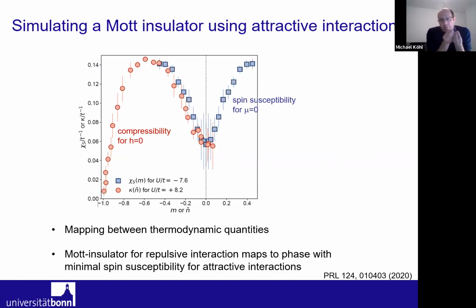Now, for the other case, for attractive interactions where we have these local pairs, we have to ask the question, what is the equivalent of the compressibility in the density sector, but now in the spin sector? And that is, of course, the spin susceptibility. So it's the question of whether we can actually disintegrate these local pairs into two free spins. And we measure the spin susceptibility spectroscopically, and then we observe directly how the spin susceptibility precisely maps the behavior of the compressibility for the density sector. So this shows that we really have a mapping between the thermodynamic quantities, between the density domain for repulsive interactions and the spin domain here for the attractive interactions, just by exchanging the roles of the chemical potential and the Zeeman field.